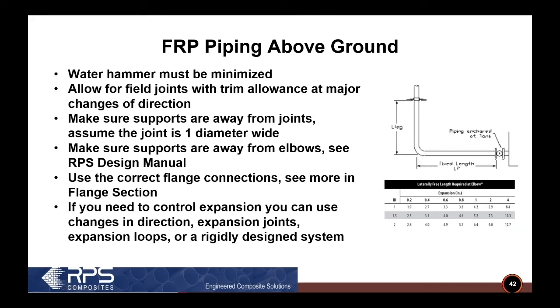To control thermal expansion, you can use changes in direction, you can use expansion joints, expansion loops, or you can actually rigidly design the piping system so you can anchor the system all over the place. Because of the relatively low modulus of elasticity, you can actually do that in FRP pipe quite nicely.